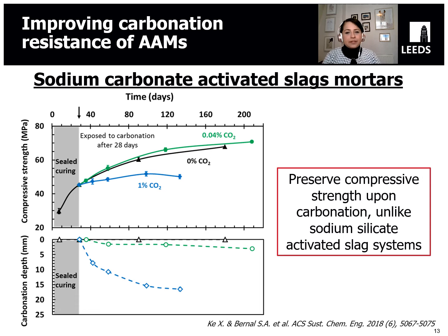Again, this is the work of Xinyuan Qi, where we exposed sodium carbonate activated slag cements to carbonation. So the formation of this layered double hydroxide has a double effect. It helps to control the kinetics of reaction. So now we were able to produce cements that will harden within expected times with desirable compressive strengths, as you can see here. But also, this particular type of system seems to be more resistant to carbonation than any other alkali-activated cement that we evaluated before when we used sodium silicate or sodium hydroxide activator.